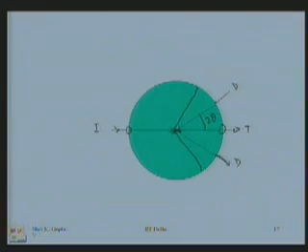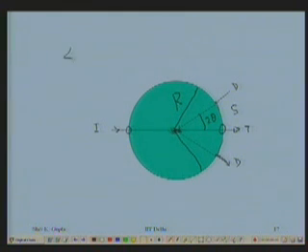While we are doing this, let us go back to the geometry of the camera. So, this angle is 2 theta and also this angle is 2 theta. The cone is intersecting at two places, making two arcs with the film. So, I can relate this: if I know the radius of the camera to be r, and the spacing between them, let us say, is s, then I can say that 4 theta is equal to s divided by r. That is the definition of the angle. And this angle is 2 theta plus 2 theta, which is 4 theta.